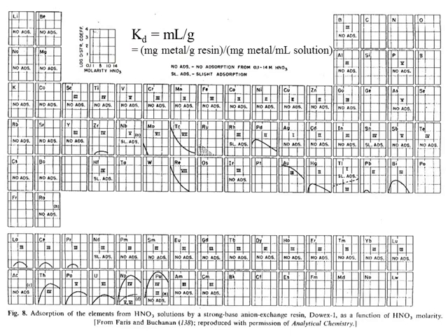And in this case, for the strong base anion exchange resin, we see that for a number of transition metals we do not form suitable anionic species with nitric acid, so there's no adsorption. For the trivalent lanthanides, there is little, and as we get to the heavier lanthanides we see no adsorption.